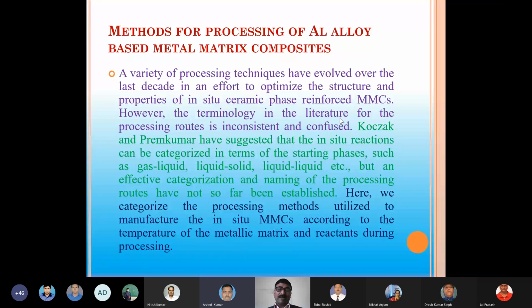So inside the melt, the titanium will react with the carbon and form the titanium carbide. Aluminum will react with the titanium and form the titanium aluminides. So you will find that it is a combination of those two reinforcement particles. Those reinforcement particles develop inside the metals, or inside the liquid metals, and hence it is called in situ metal matrix composites.